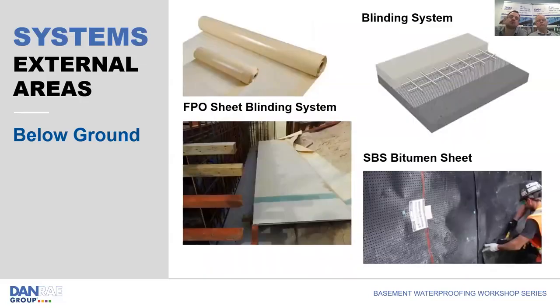Some more systems that we've used. The top two are what they call blinding membranes. These are installed onto the formwork before you pour the concrete, and then your formwork's stripped off. What happens there is it forms either a chemical or mechanical bond to the concrete itself.